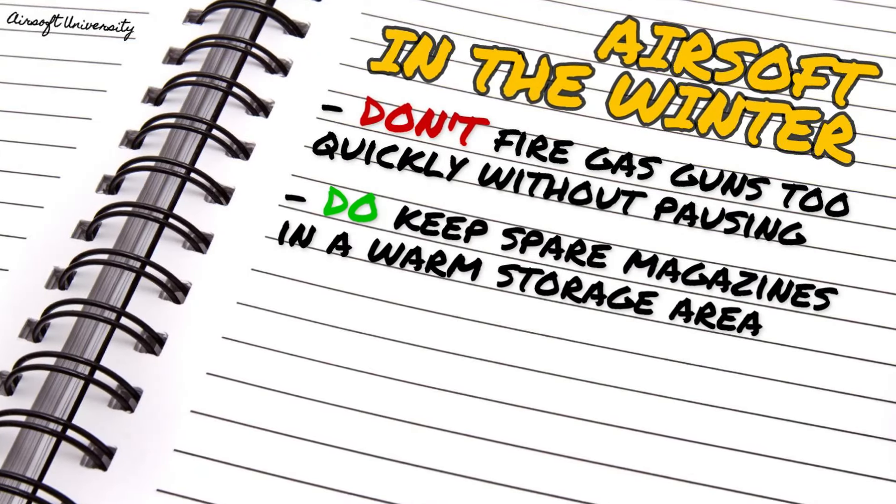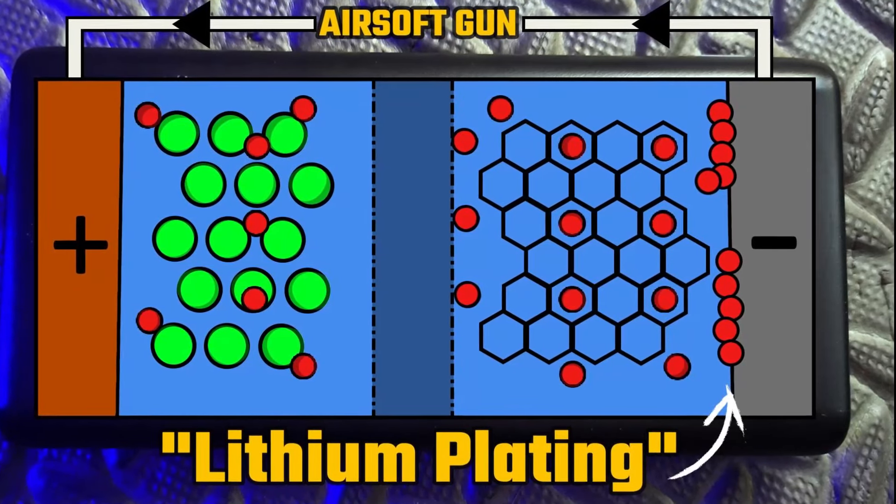What about batteries? Surely the quickest way to keep them warm is to just keep firing, which will promote the flow of electricity through the system, right? Well, technically yes, that can warm it up, but not for long and not in the way that you want. Because of the increased current needed in cold temperatures, you'll not only be draining your battery faster but also decreasing its overall lifespan. This is the same reason that we don't want to ever charge our batteries while they're in the cold — anything under zero degrees Celsius — as it leads to the problem of lithium plating that we mentioned before.